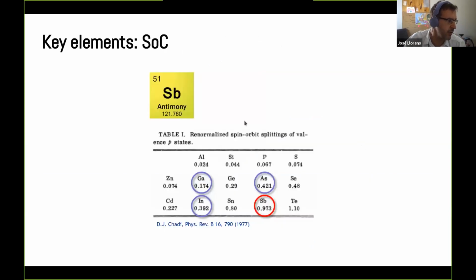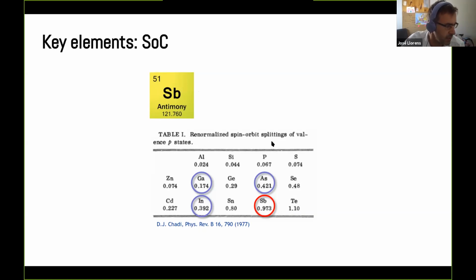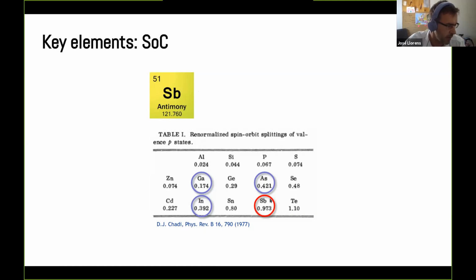The other ingredient is to have strong spin-orbit coupling, to transfer this control on the wave function, the orbital part, to the spin of the state. For this, we rely on antimony, because antimony is, among all the III-V semiconductors that can be used in an MBE chamber or MOCVD to make electronics based on GaAs technology, gallium arsenide technology, the one with the highest spin-orbit coupling.